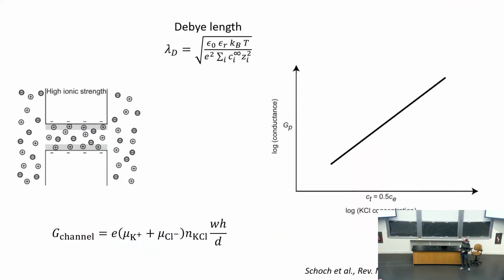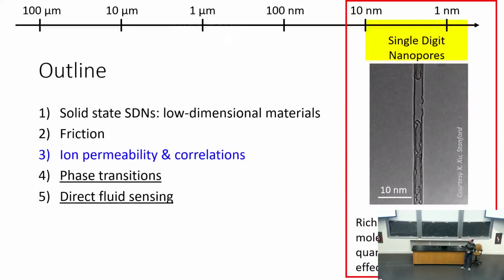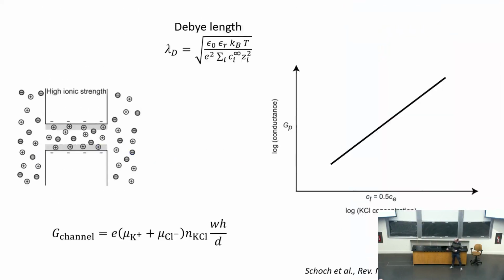Okay, moving on. I want to say another case study is about ion permeability and correlations. So when you have a pore in a solid state system like this, what is known is that if you have ions in your solution, they will come and screen surface charges in this pore. Surface charges are pretty much ubiquitous. It's hard to have a system where there is no surface charge. So generally there is, and ions will come in and screen, and the length over which the charge is screened is determined by the so-called Debye length, which depends on the inverse of the square root of the ionic strength. Ionic strength being essentially the concentration of your ions.